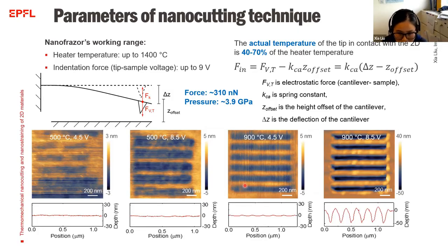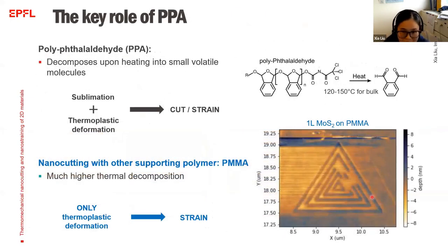So then I apply a high temperature to make the PPA sublimate. I apply 900 degrees. So you can see at high voltage or high force, we can easily cut the 2D materials, but at the low temperature, at the low voltage, we cannot cut. It means sufficient force is needed to break the 2D material, to make the PPA evaporate, and to have the indent created. From the calculation, we can see the PPA plays a very important role in this technique.